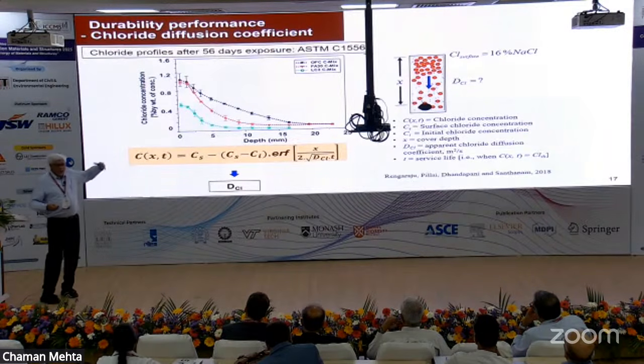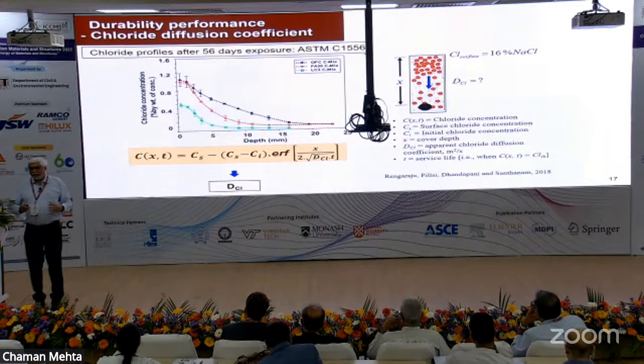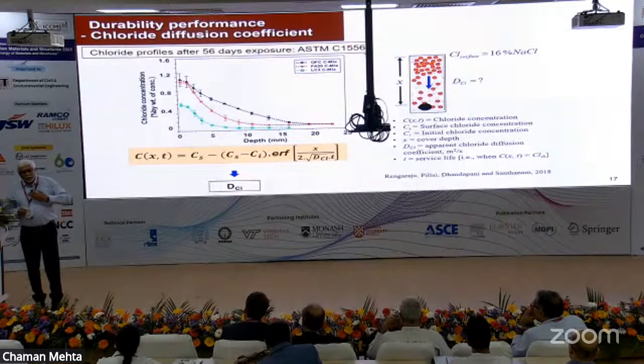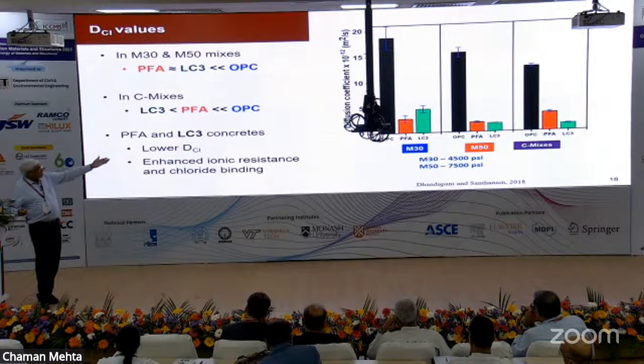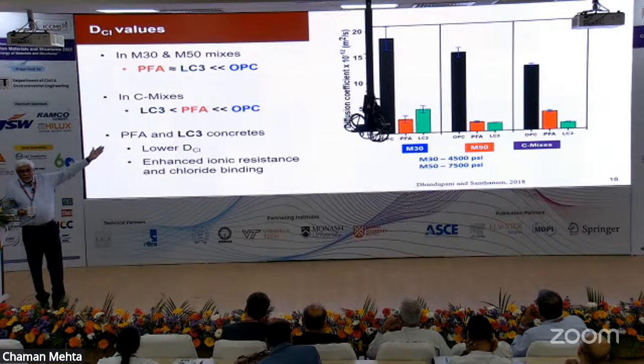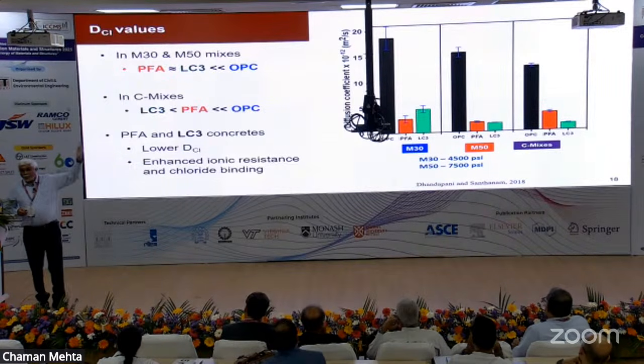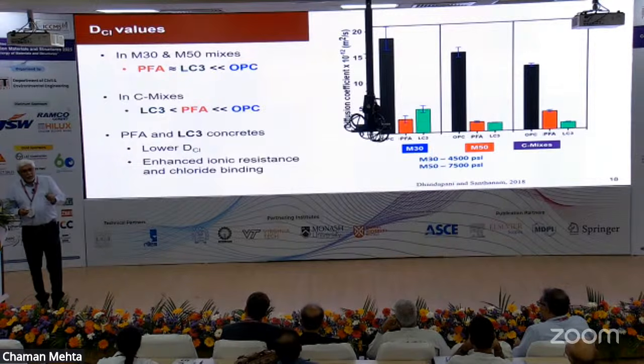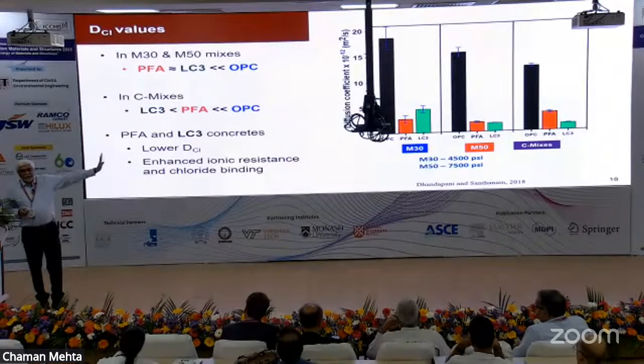Very clearly, I'll show you this and I'll show you diffusivity. So again, diffusivity. We took concrete, put it in salt solution, and what diffuses in is faster when you just have ordinary Portland cement. Fly ash, slag, and so on will slow this down. That means your cover is protecting the concrete better. So there are a lot of good things that we can take advantage of. Diffusion, the black bar is ordinary Portland cement. Concrete is allowing chlorides to go in much faster than the blended binders. Okay, so for durability under chloride attack, very clear you get longer life with blended binders.